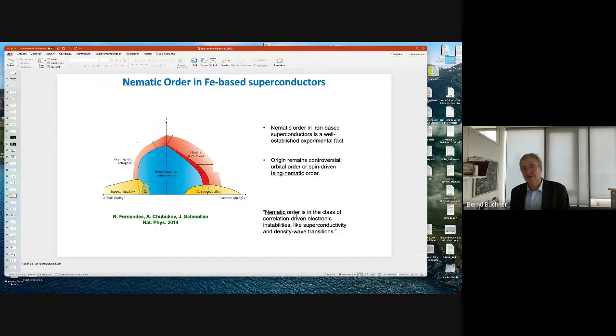And this is now a phase diagram which has been put forward by theory colleagues. It's this barium 122. And there you again see this parent compound, which is magnetic. This is this blue stuff. And then, well, the situation is slightly different, but qualitatively you also have a structural phase transition. In this material, it comes at the same temperature simultaneously. And then we also go to the orthorhombic phase. So we have this connection between magnetic states occurring in close proximity to this structural phase transition.